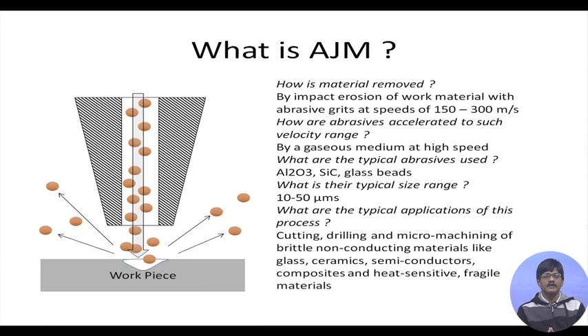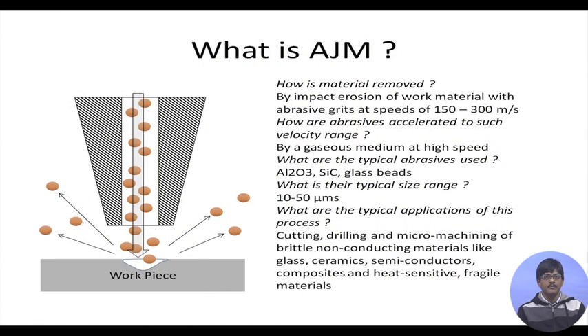But the main thing is that they have very high hardness and very high form stability, and therefore, when they hit the workpiece surface, they generally cause fractures due to impact. And when these fractures accumulate, they produce damage, which we refer to as material removal, and we can create grooves and cuts, or drill holes, by this method in such hard, brittle and non-conductive materials. Conductive materials also, but for conductive materials there are other competing processes, while for hard, brittle, non-conducting materials, this process is almost without any competition.